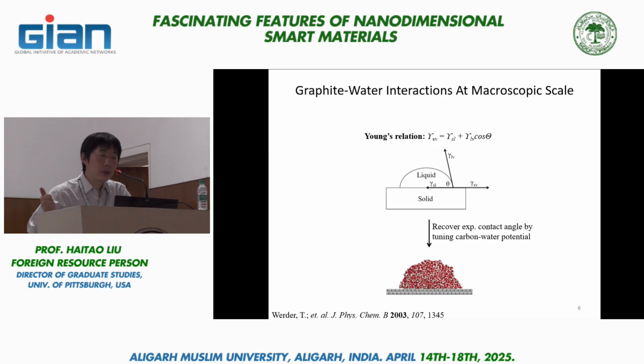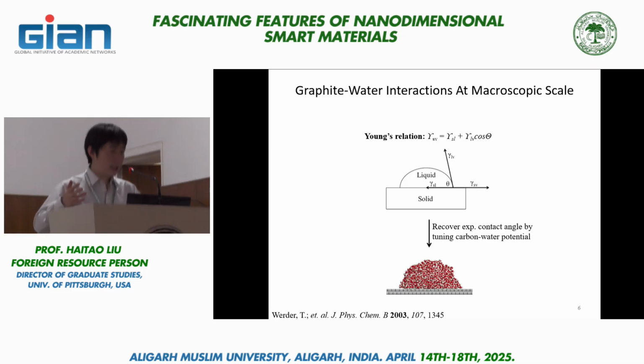situations. What you can do then is come up with some kind of model, let's say a molecular dynamics simulation. You can put in parameters to describe a very generic water-carbon interaction. Maybe you don't know the exact magnitude of this interaction, but it doesn't matter. You can just tune them, change them to whatever number you want, and run a molecular dynamics simulation, and for every simulation you run, you can get the calculated contact angle. You can change the parameter until the simulated contact angle matches experimental data. Very simple to do. Obviously, you have to take into account size effects and so on, but in principle, you can use this very simple measurement